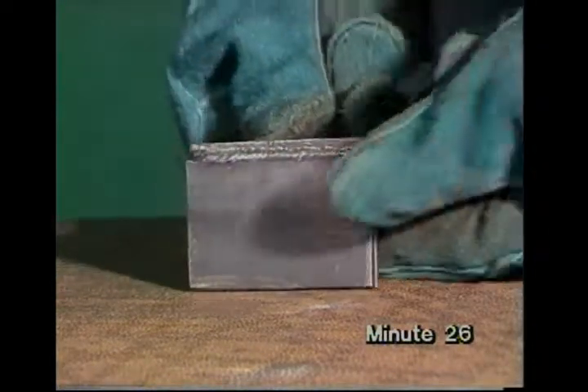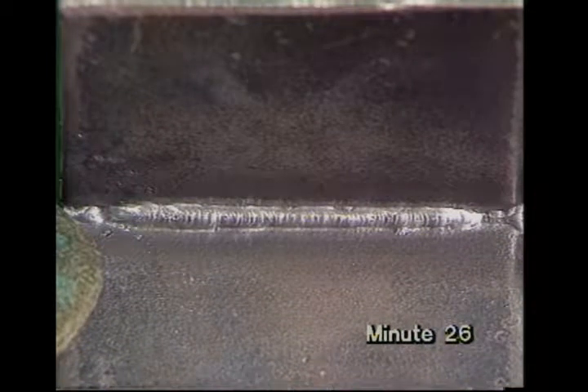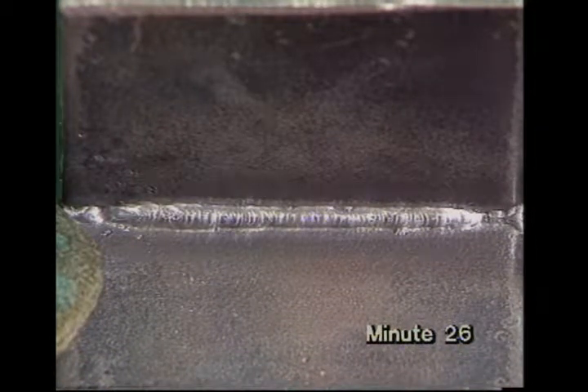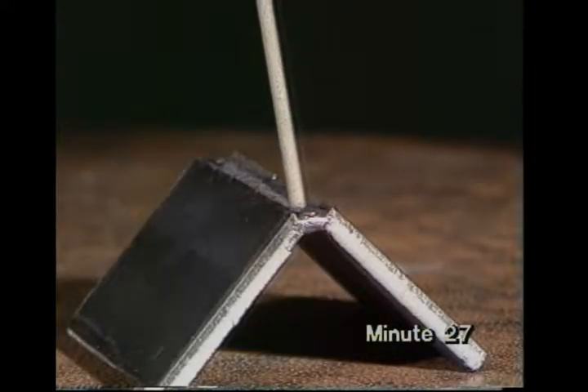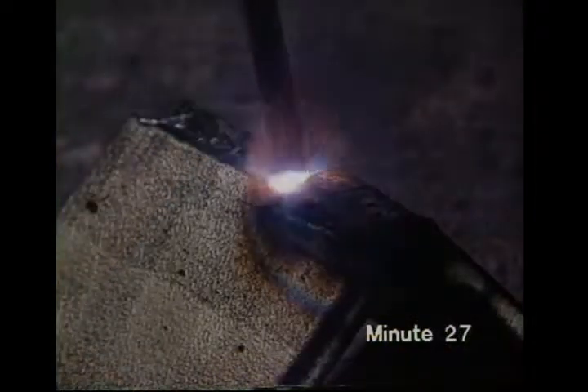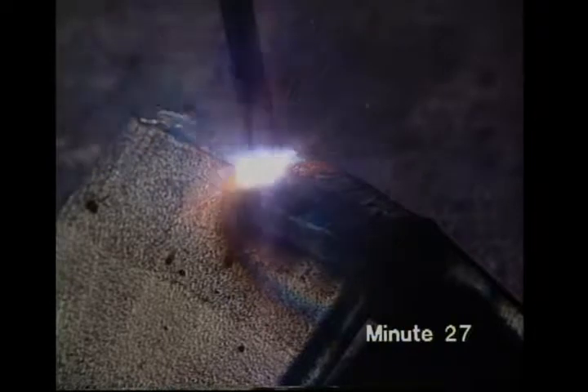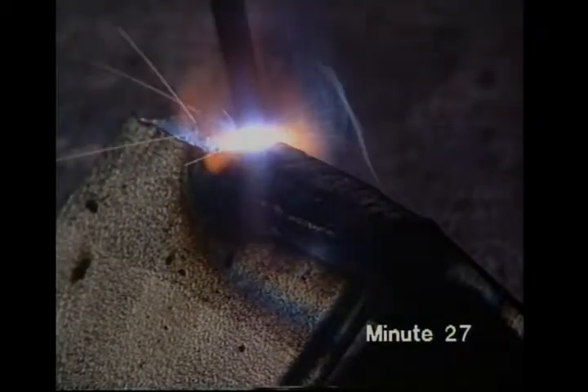If you could look at the weld from underneath, you'd see how the metal melts right through the joint. When you've finished, turn the joint over to make sure the weld metal has penetrated through to the inside. As you won't have filled the joint with metal, make a second run with weaving. Pause at the sides for good results. The macro section shows that the weld metal fills the joint with a reasonably smooth top and bottom surface.